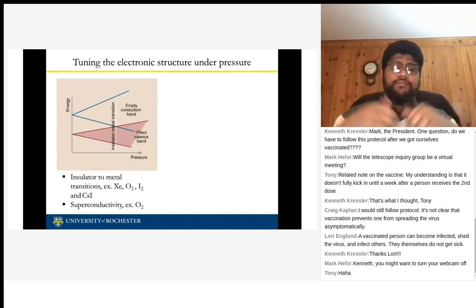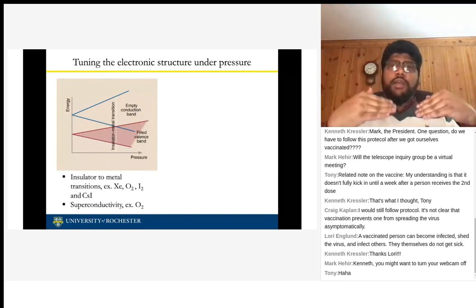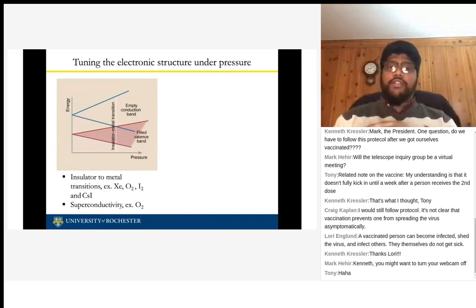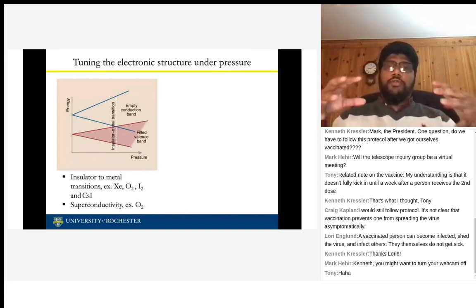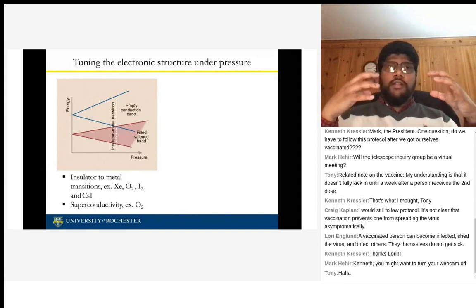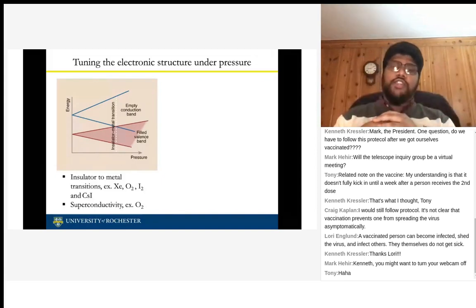The same way with hydrogen. Pure hydrogen at ambient condition is a gas. But if you subject it to really high pressures, 500 gigapascals, it becomes metallic hydrogen. And in planetary interiors, people are thinking of Jupiter, that hydrogen may be in liquid form, liquid metallic hydrogen. Because if the PT conditions are correct, you may very well have metallic hydrogen in these planetary interiors. So you see that with pressure, the properties of a material can change dramatically.